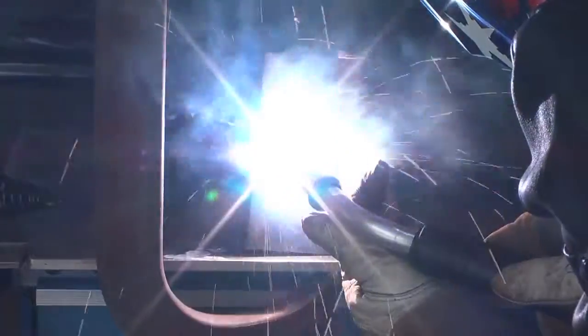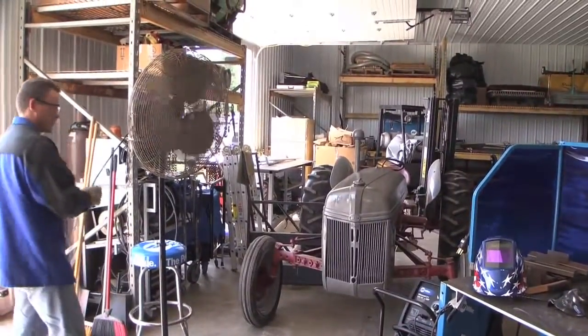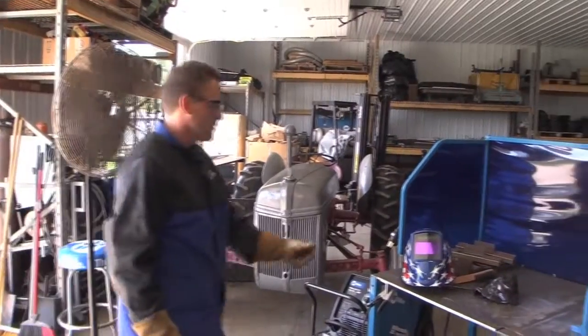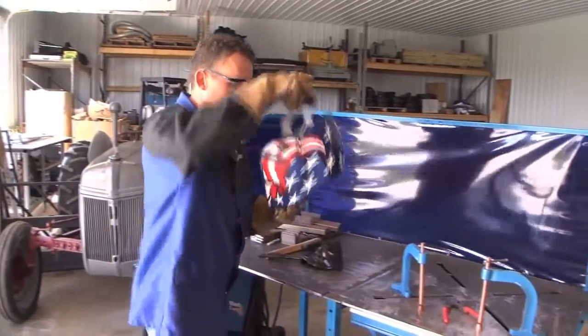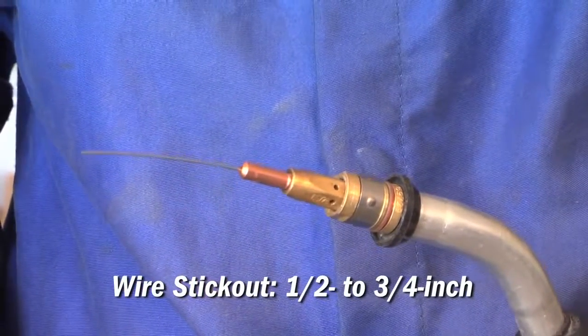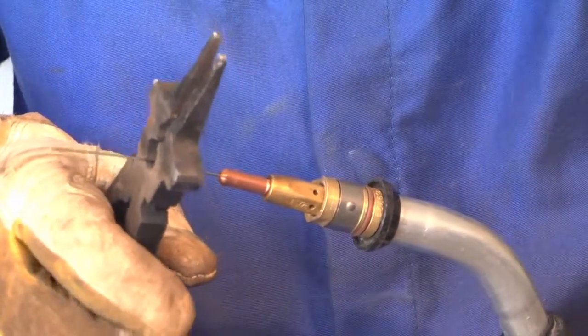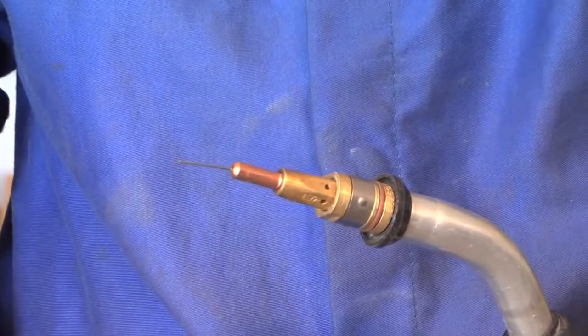Flux core welding produces a lot more smoke than typical MIG welding. It's a good idea to make sure you have adequate ventilation. If you're indoors, just make sure you turn on a fan and open a door. The wire stick out should generally be about 1/2 to 3/4 of an inch from the contact tip, possibly a little longer for tight joints.